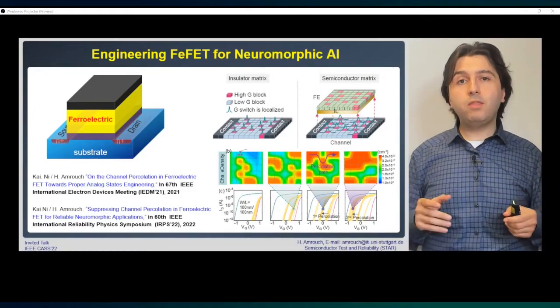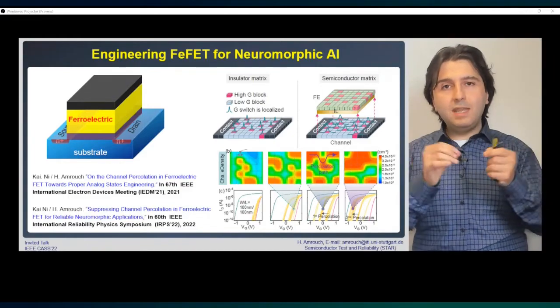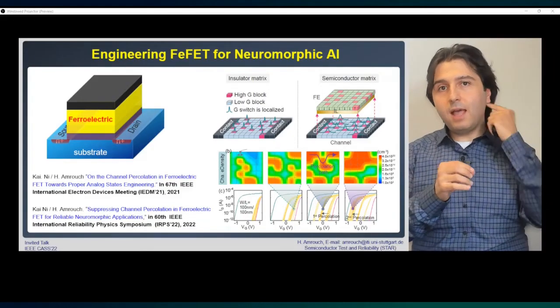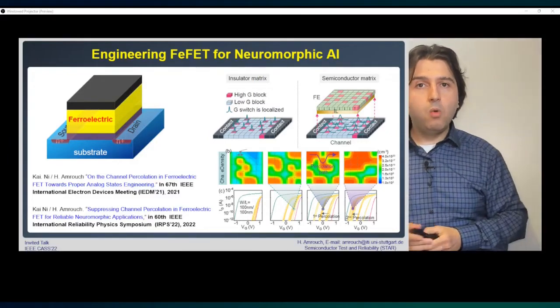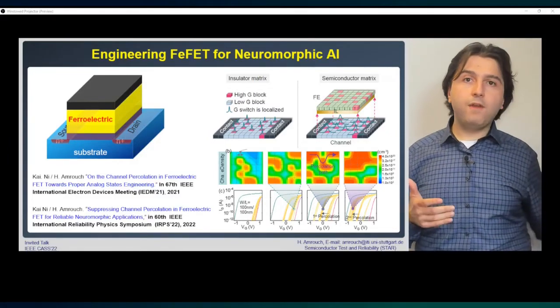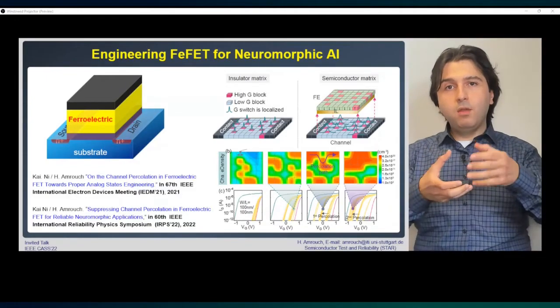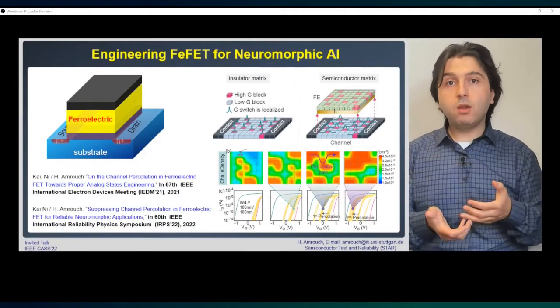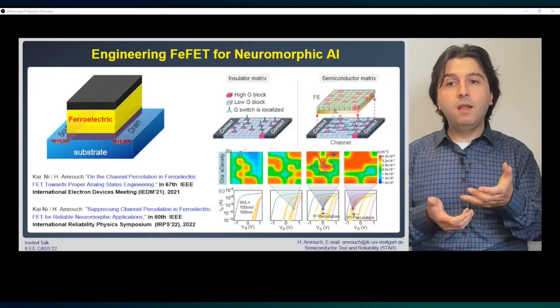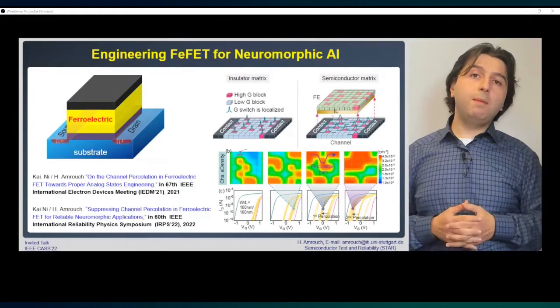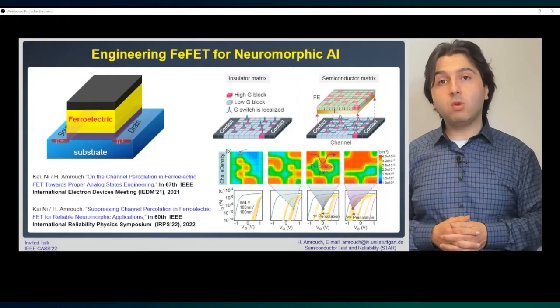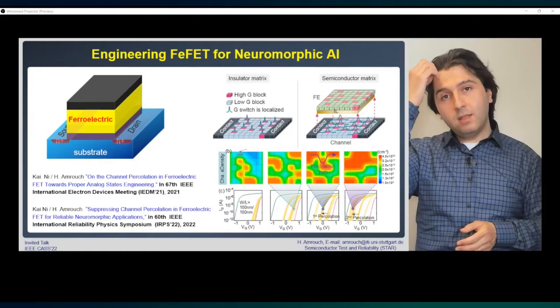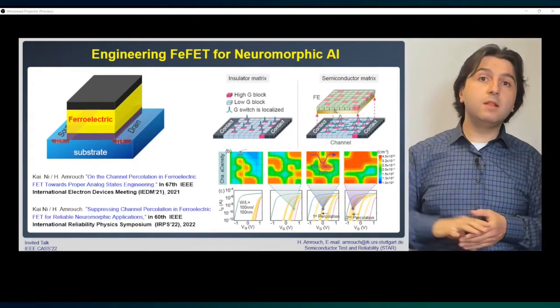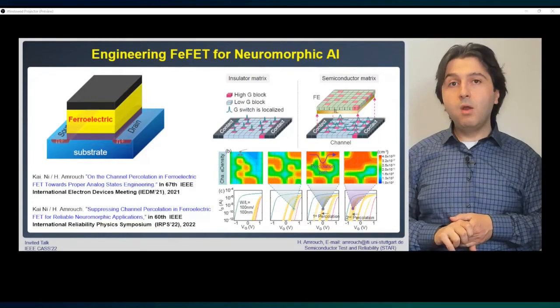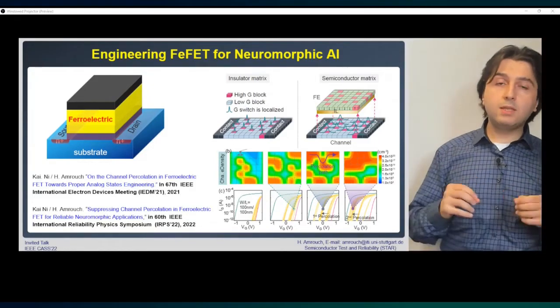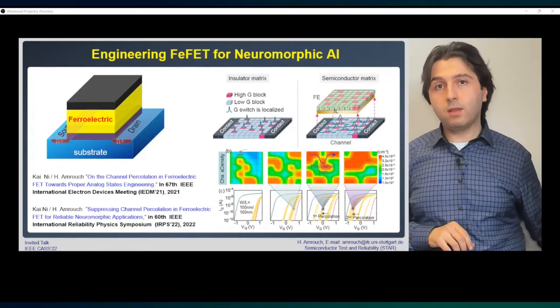And to model that, you really need to go to the extreme low level, which is the fundamental atomic or material level, where you can mimic what the ferroelectricity is doing by charges, and then do very expensive Monte Carlo simulations at the material level, in order to see how the transistor would be impacted due to the inherent stochasticity in the ferroelectric. If you are interested in this, based on your background, we recently had a paper in the International Electron Devices Meeting, IEDM, where we showed for the first time how such stochasticity can be modeled and studied in ferroelectric transistors.